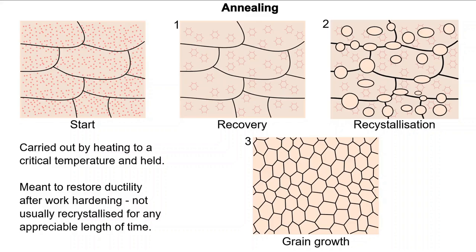For the most part, annealing is carried out statically. A component is placed in a furnace and held at a temperature well below any phase change, and then slowly cooled. Usually this is conducted to restore some ductility after plastic deformation without affecting the strength too much. Higher temperatures and longer periods of time at these temperatures will result in the latter stages of annealing. Let's look at the relative effects of each of the three regimes of annealing on some mechanical properties.